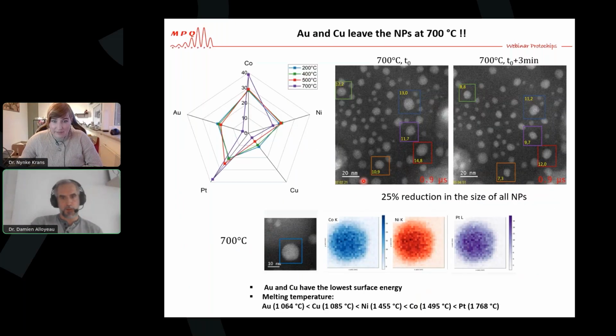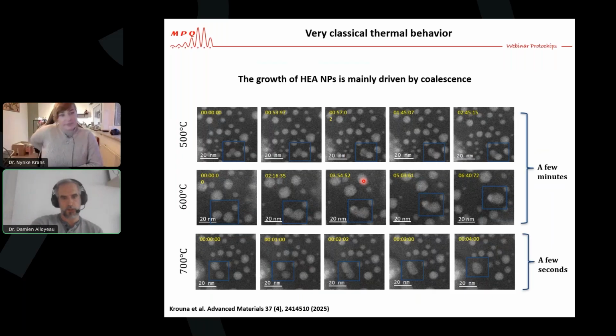Okay, so first of all, during the coalescence, I think he talked about this image. Of course, there will be channeling, but we look at those images at low resolution. There is no doubt that there is a segregation of the different metals within the nanoparticles on those images. I'm not sure I understand what he means by exothermic. To me, it's thermoactivated. We tried to observe this process at high resolution, but it was quite challenging on this system.